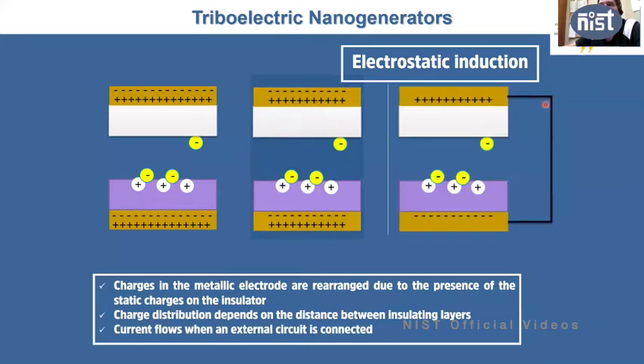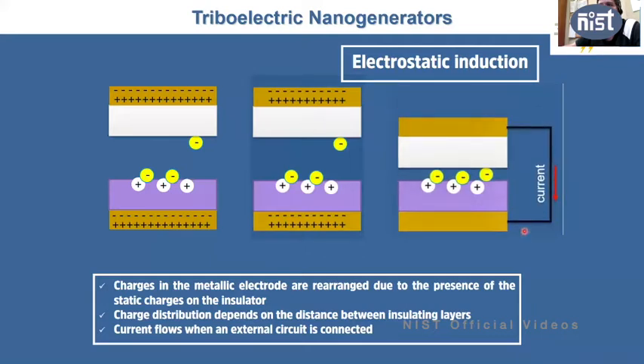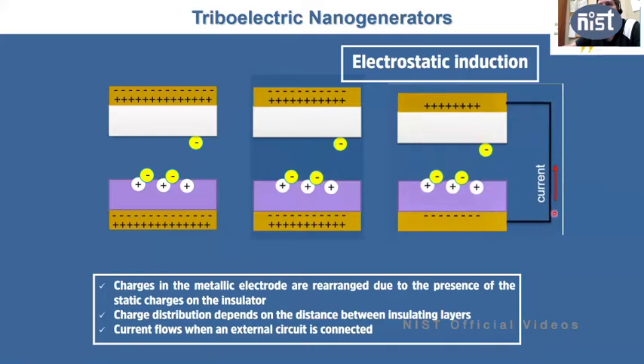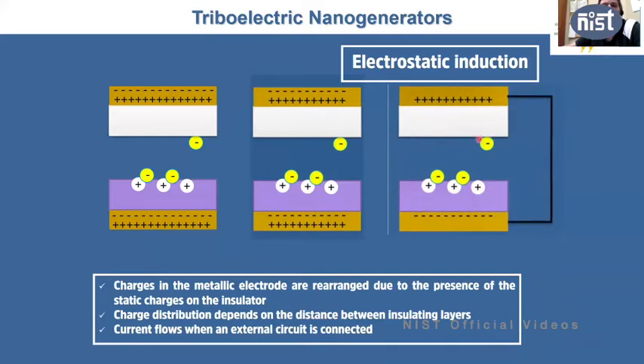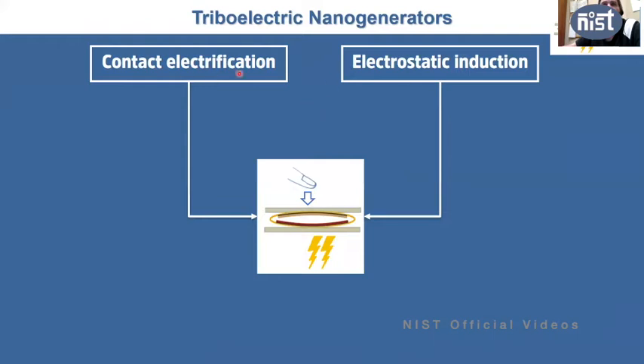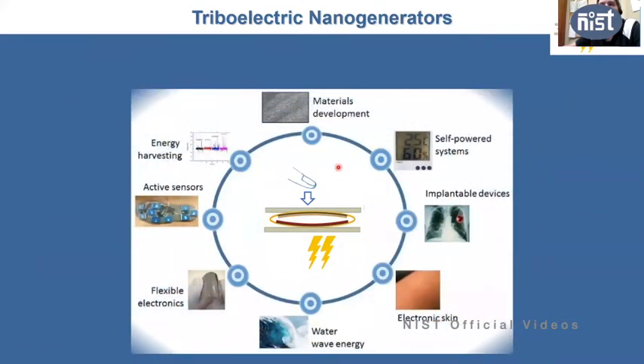If you now connect a resistance between these two materials, what happens is that as they come closer, the current will flow from one electrode to the other. And as they move backwards, the current will flow again and the charge redistribution will appear. So with this electrostatic induction, you have the possibility to drive charges through an external circuit. If you join the two things, contact electrification that gives you the charges on the surface of the charged materials, with electrostatic induction that gives you the possibility to have the charge flowing through the external circuit, you have a triboelectric nanogenerator. This has been developing very fast since 2013, and there is a whole range of applications that you can get from these devices.